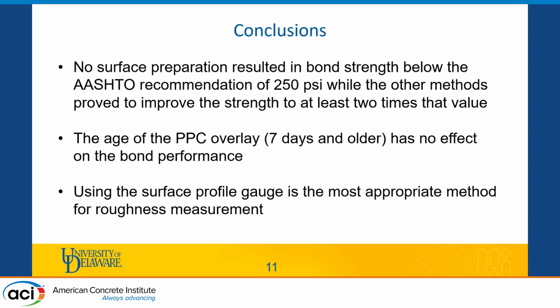We were testing the bond strength, and since for all the methods the failure was recorded higher than the requirement of AASHTO, it wasn't so important, but we still wanted to see when it fails, what's the limit. So when it failed in either the UHPC or PPC, it means the interface is even stronger than those two parts, or the one that failed more specifically. When we chose the failure at the interface core in depth, we wanted to move forward with that to test the interface the most compared to the other two regions.